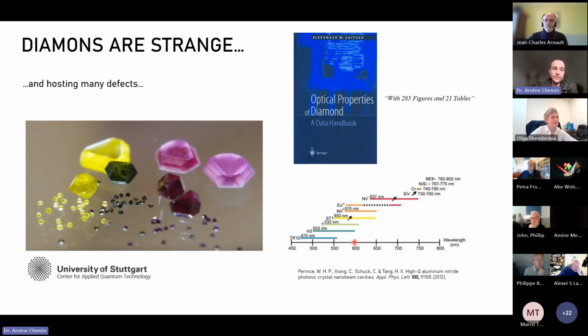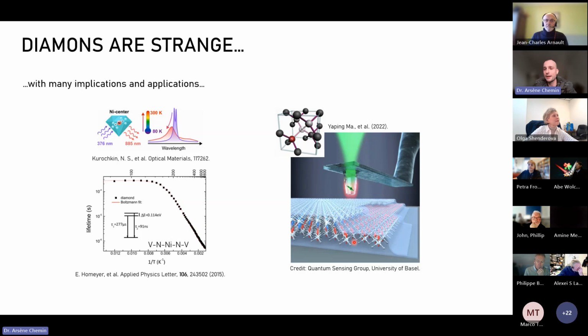And those defects are actually very useful. I guess many of you here know about NV centers that can be used for quantum probing. I will talk more about that at the end of the talk. But there are also many other defects, and a colleague of mine, Gilles Ledoux at the Institut Lumière Matière, worked extensively on nickel nitrogen vacancies that can be used to measure temperature in a system. You can disperse nanodiamonds with those kinds of vacancies inside a medium, for instance a liquid, and look at some cavitation effects, probing the local temperature. So diamond has many, many uses, and many of these uses come from the defects.